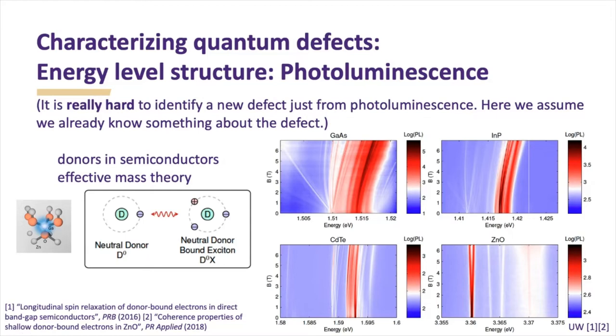It's different from a hydrogen atom in that its Bohr radius is much, much bigger. For example, in gallium arsenide, the Bohr radius is 100 angstroms, whereas a hydrogen atom is only half an angstrom. And in zinc oxide, that Bohr radius is about 10 angstroms. So these are very large. And what's nice is that in direct band gap semiconductors, so unlike silicon, you do have this optical transition to something called a donor-bound exciton.